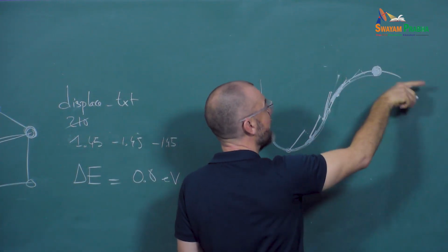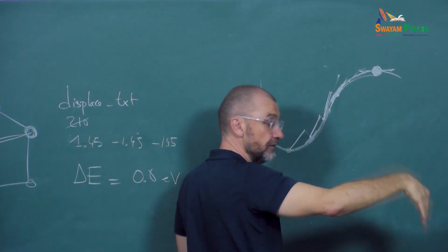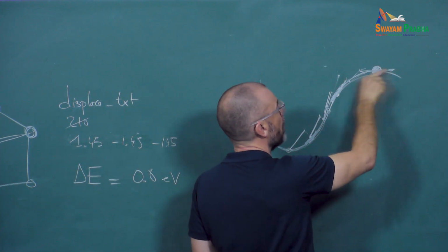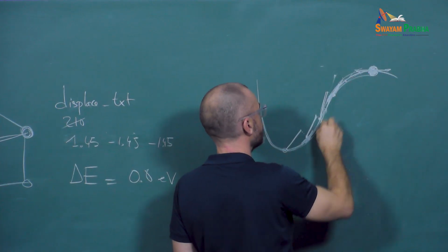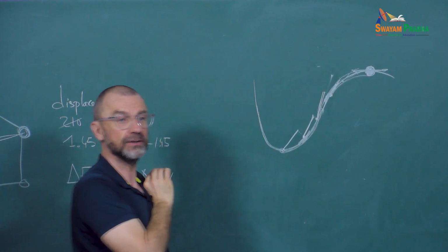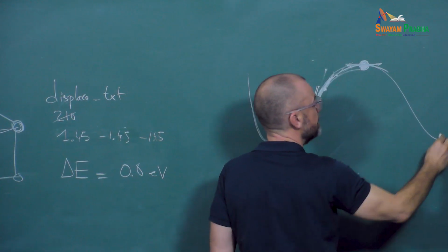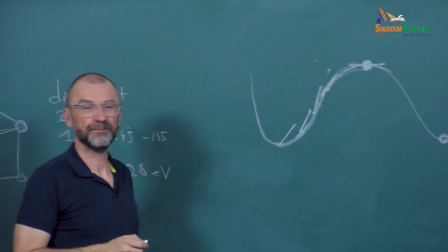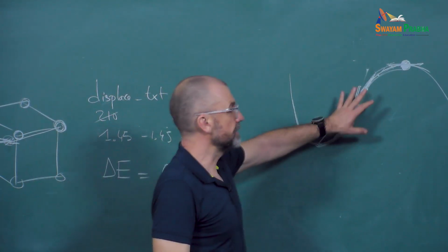Once I am at the saddle point, then I can add a perturbation. I have an eigenvector at the saddle point, the eigenvector of a negative eigenvalue. I can perturb the system along that vector backwards and do a new energy minimization to make sure that I am still connected with the initial configuration. And then I add a perturbation in the opposite direction and I do an energy minimization, and that will give me the final configuration. You see the idea?